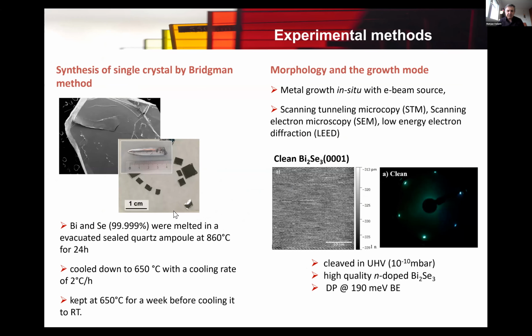We are growing our single crystals by ourselves using the Bridgman method. We just seal metals into a quartz ampoule, melt the metals down, and then slowly cool it to obtain such ingots as you see here. And it's fairly easy then to extract single crystal flakes out of such an ingot. And now if we look at the structure, the surface of such a flake, we have done this with different methods.